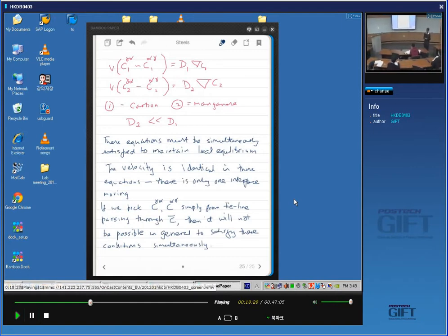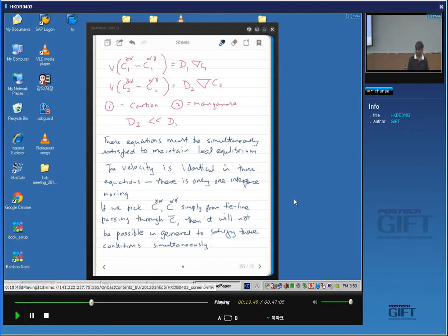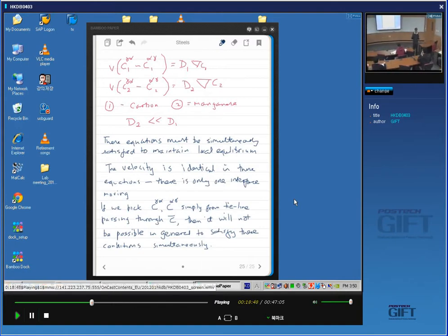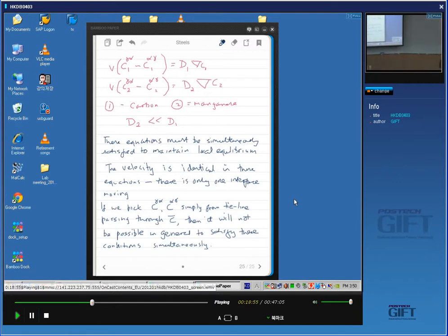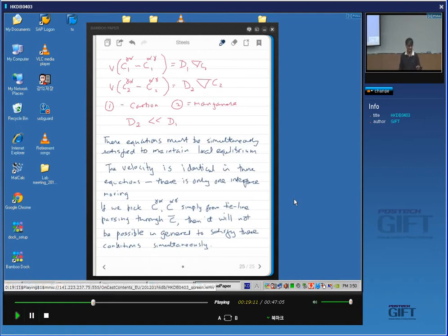So one possibility is to choose a tie line from the very large number available on our ternary phase diagram such that the gradient of carbon is reduced, and then the flux of manganese can keep up with the flux of carbon. We now have a choice of tie lines, not a single tie line which passes through C-bar. Given that choice, if we pick a tie line which minimizes the gradient of carbon, the product of the large diffusion coefficient and small gradient will become comparable to that for manganese. The second solution: if the diffusion coefficient of manganese is very small, pick a tie line which maximizes the gradient of manganese, so that the product of a small diffusion coefficient times a large gradient might be comparable to that for carbon.